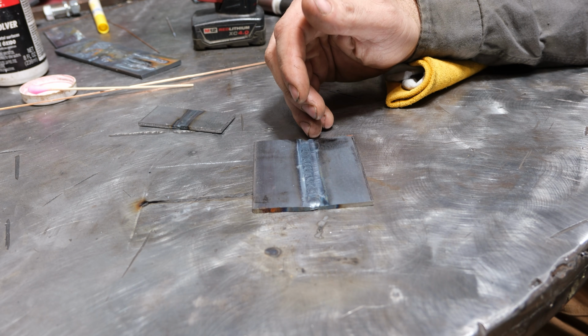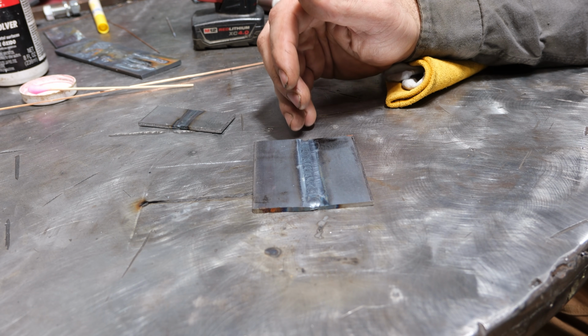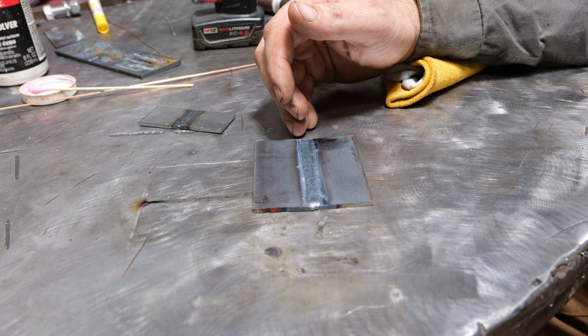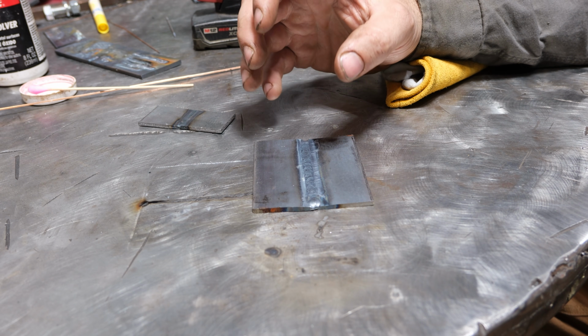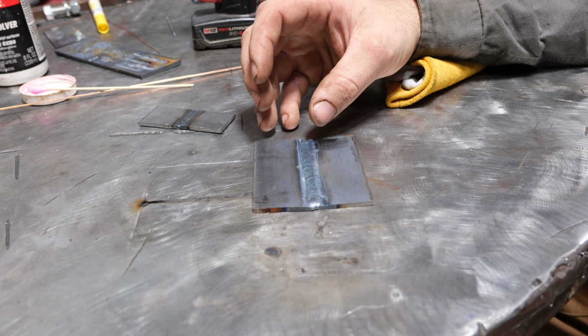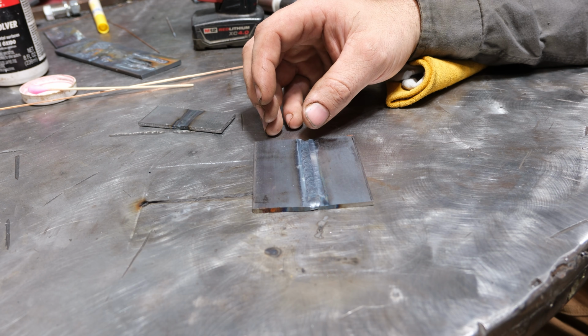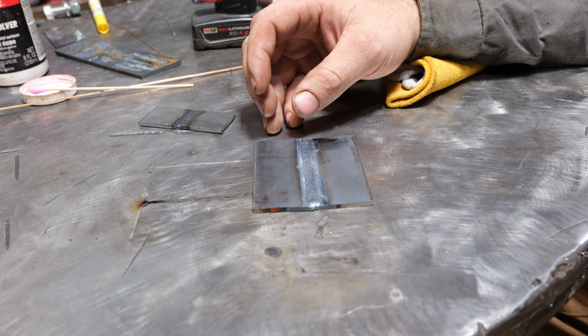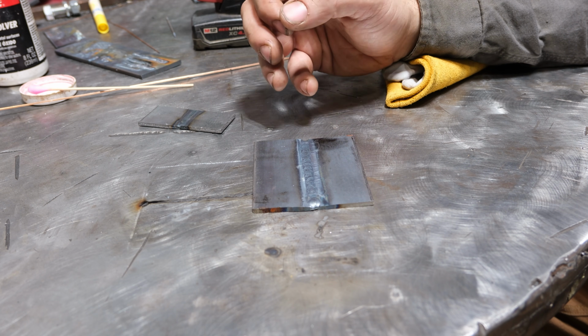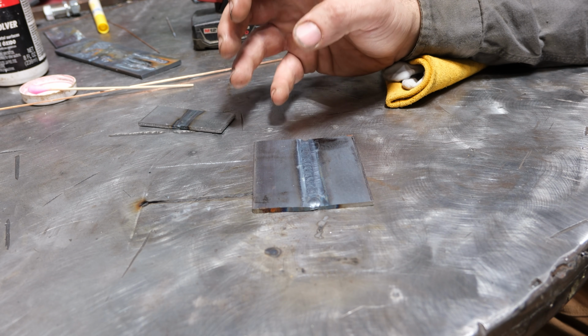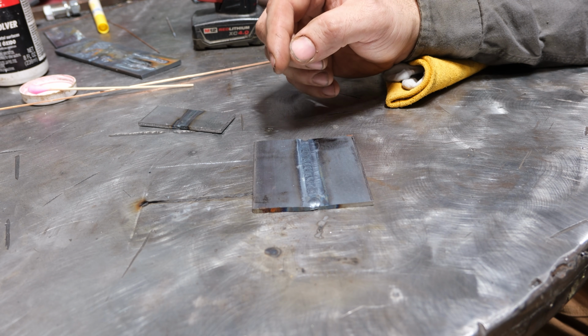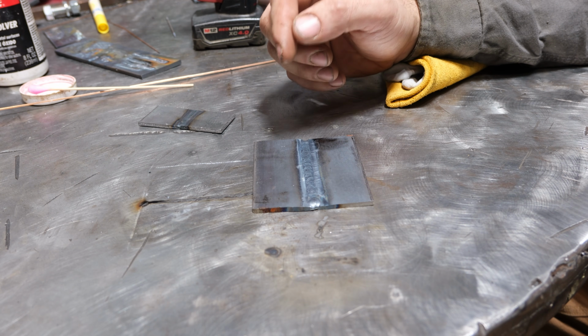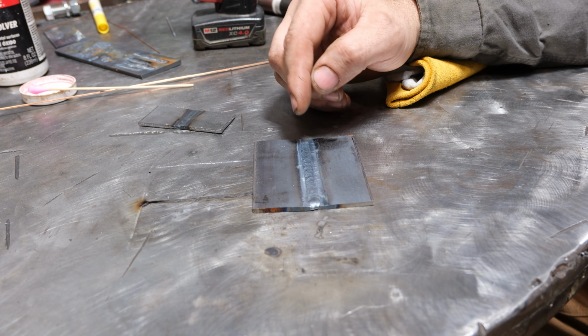And in the case of what we got here, going back over it with another pass to bring the reinforcement out will make a very strong weld that will likely not fail. Far better than just running a single cold pass and having no weld depth per se. Now, there are ways to achieve full fusion in one pass with the proper amount of reinforcement out the face.